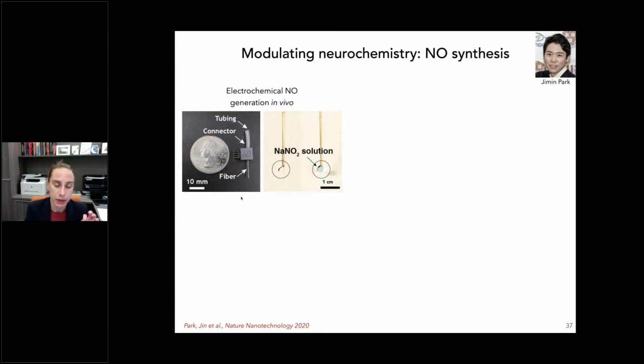And those fibers are made such that we can draw them in a custom process with the electrodes that will act as our electrocatalytic electrodes, as well as a microfluidic channel that will supply our precursor, sodium nitrite, into the brain. These devices are quite miniature. Those fibers are a couple of 100 microns in diameter, and they contain 2 electrodes, a gold-coated tungsten and platinum-coated tungsten, and we coat our iron sulfide clusters onto gold-coated tungsten electrodes, creating a cathode, and then the counter electrode is coated with platinum.